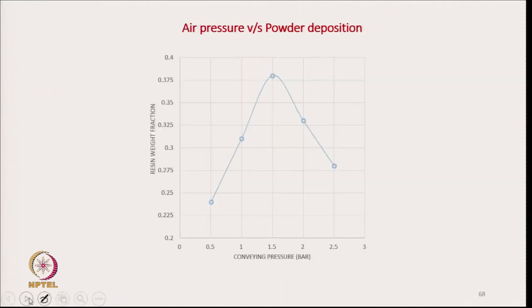Once the powder particles reach their saturation limit as a result of the increase in corona voltage, increasing the voltage further does not help. So, we can say around 50 to 60 is the optimum voltage which we can use here.